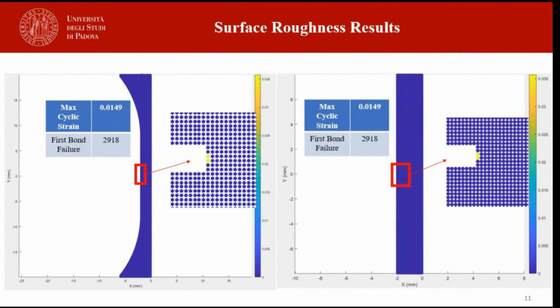To reduce computational time, we only consider the gauge section here. However, it is important to verify the effect of this simplification on key results like maximum cyclic strain and first bond failure. As we can see, their values are the same, so for simulation, we can consider only half of the gauge section. In addition, the height of the gauge section is also reduced to 4 millimeters in order to achieve faster simulation.